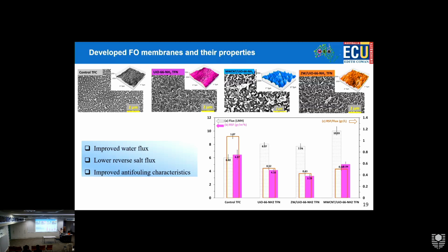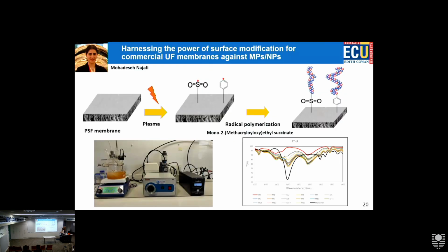We have higher flux and lower reverse salt flux in that case, which was observed in this case, zwitter ions. And the next double modification also showed higher performance compared to the other 2 cases of single modification and control TFC. And overall, with the integration of these materials, we could get better performance and anti-fouling properties as well.